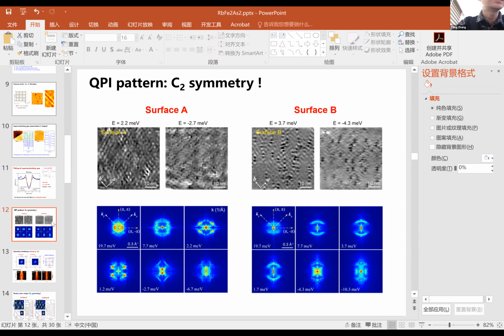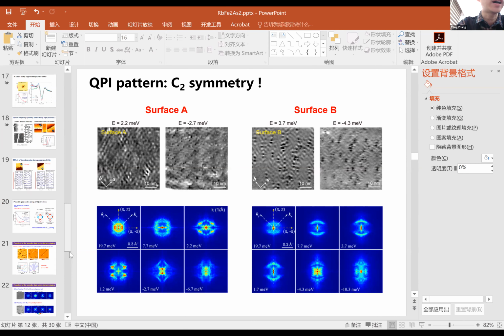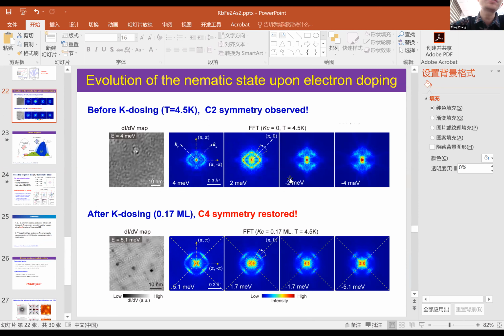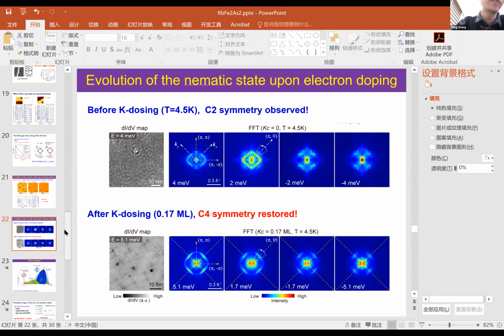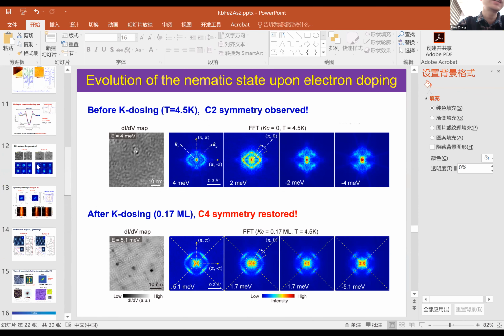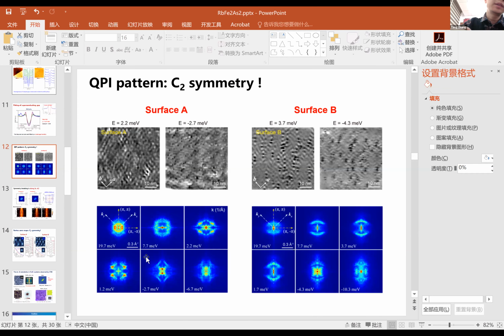Right. This data set is measured below the Tc. But we also checked the QPI above the Tc here. It shows similar patterns. You are right, the QPI may also give you information on the gap structure, and we tried that. But to be honest, the pattern is not clear enough to extract the information. So far, we cannot get useful information about the gap structure from the QPI.